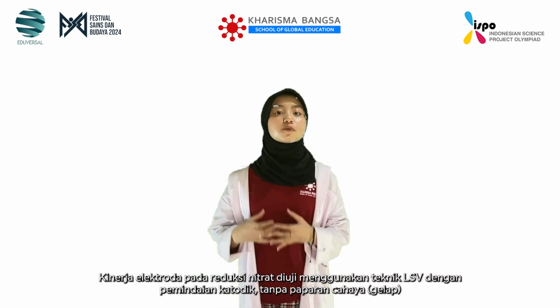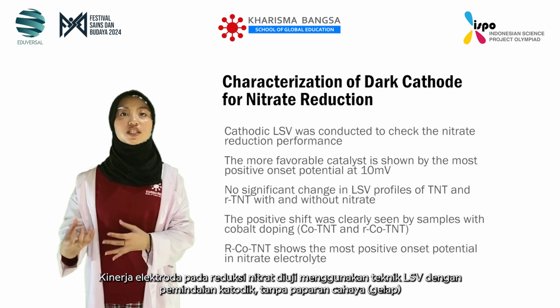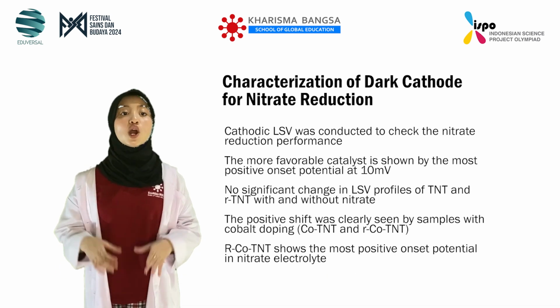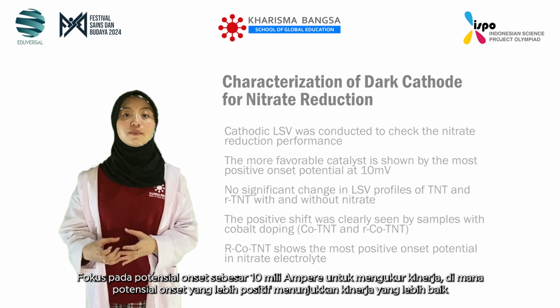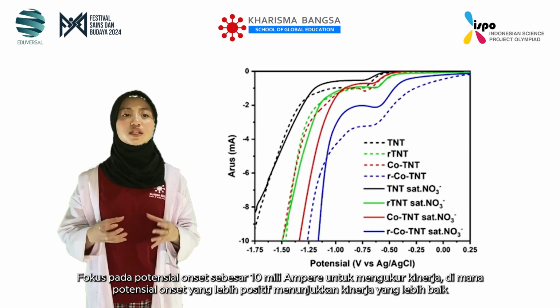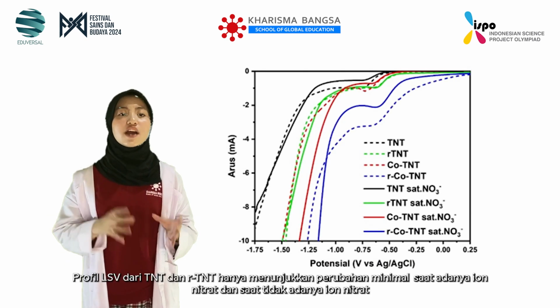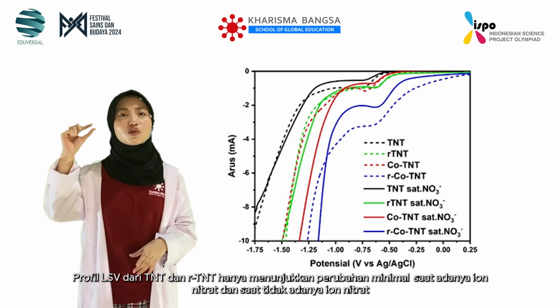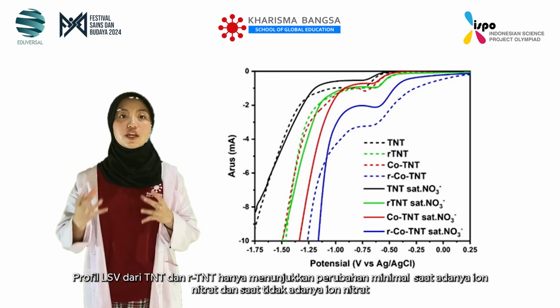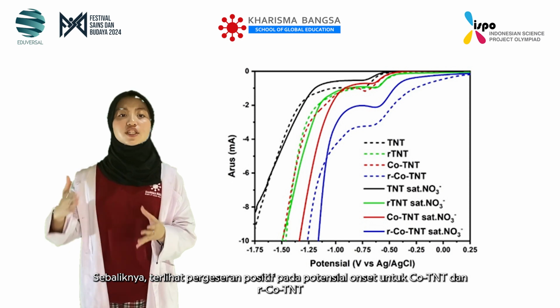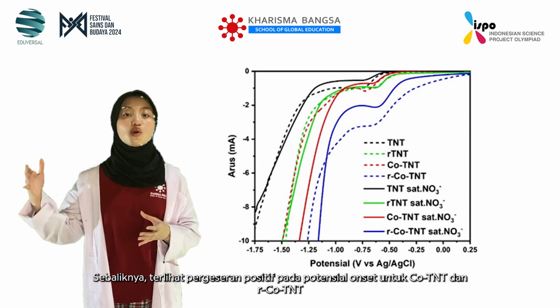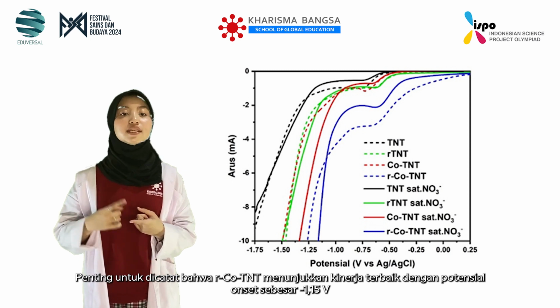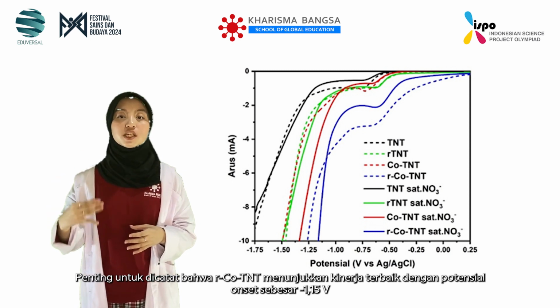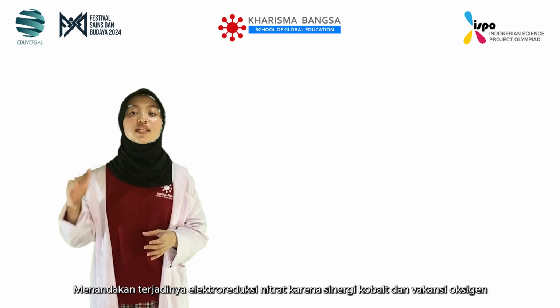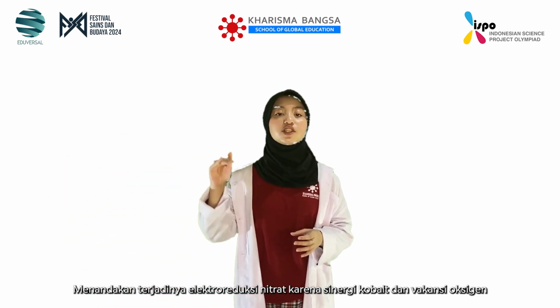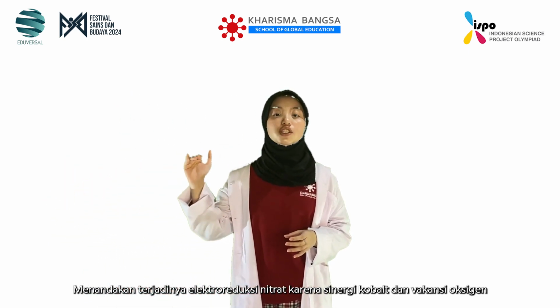The synthesized electrode's performance in nitrate reduction was assessed using LSV with cathodic scanning without light exposure. We focus on the onset potential of 10 mA to gauge performance, where a more positive onset potential indicates better performance. The LSV profiles of TNT and RTNT showed minimal changes in the presence and absence of nitrate ions. In contrast, a positive shift of onset potential was observed for Co-TNT and RCo-TNT. Notably, RCo-TNT exhibited the best performance with the onset potential of minus 1.15, signifying the preferential occurrence of nitrate electroreduction due to the cobalt and oxygen vacancy synergy.